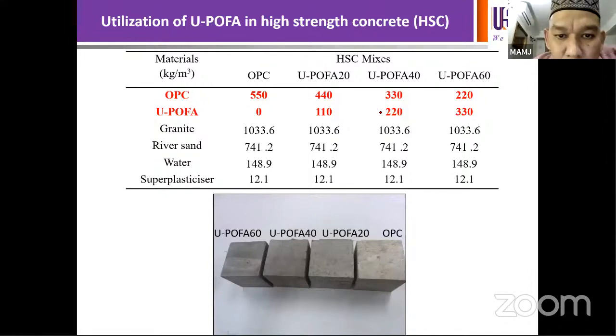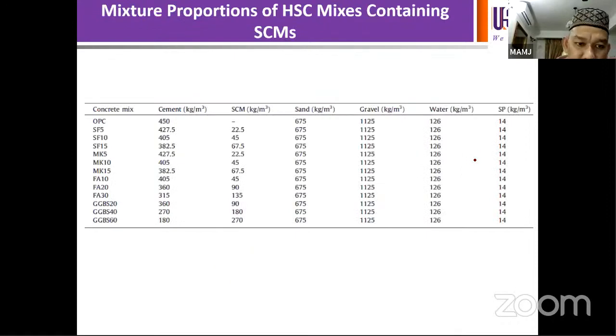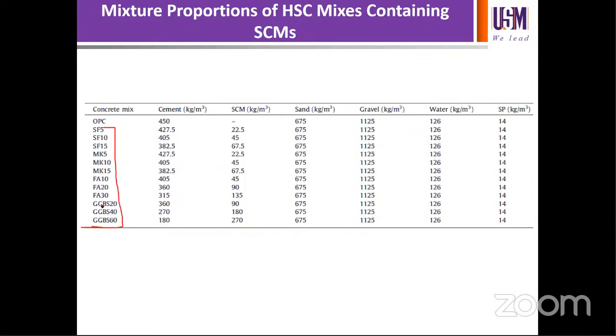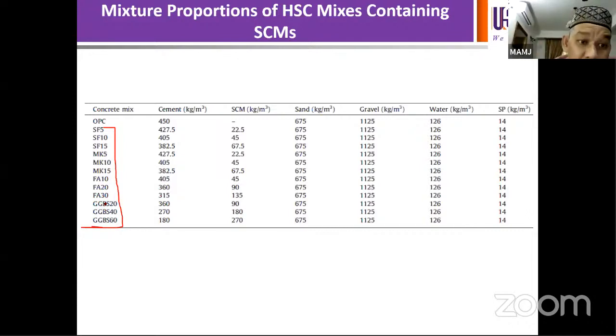So we have used this material to produce high strength concrete. The POFA was used to produce high strength concrete at 20%, 40%, 60%, meaning we replaced the ordinary Portland cement content at 20%, 40%, and 60%, while other materials remain the same. Similarly, the other supplementary cementitious materials, silica fume, metakaolin, fly ash, and ground granulated blast furnace slag, have also been used to produce high strength concrete at various replacement levels: 5, 10, 15 for silica fume, and metakaolin also the same, 5, 10, 15, fly ash 10, 20, 30, and slag 20, 40, 60%. So in this 60% slag concrete, the ordinary Portland cement content is only 40%.